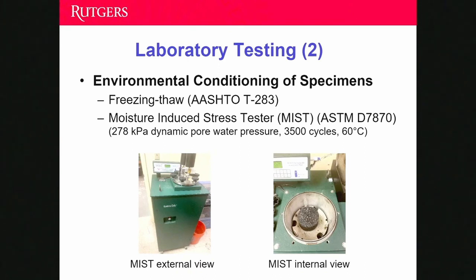The second environmental conditioning is that we loaded dynamic pore water pressure on the specimens using a device called the moisture-induced stress tester, also called MIST. As we can see from these 2 pictures, we put the Marshall specimens in this cylindrical chamber, filled it with hot water, and sealed it. There's a bladder inside which can inflate and shrink to apply the pore water pressure. Based on the standard, the magnitude of the pressure was around 280 kilopascals, and the water temperature was 60 degrees C. We applied a total of 3,500 cycles for each conditioning.